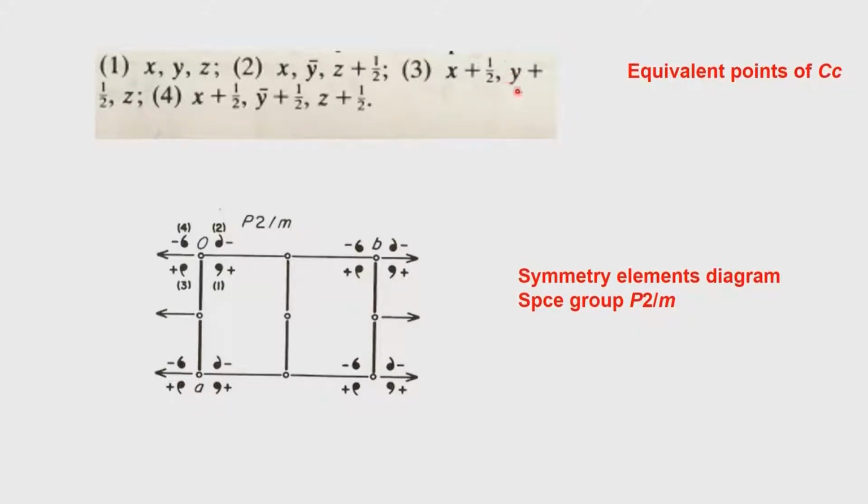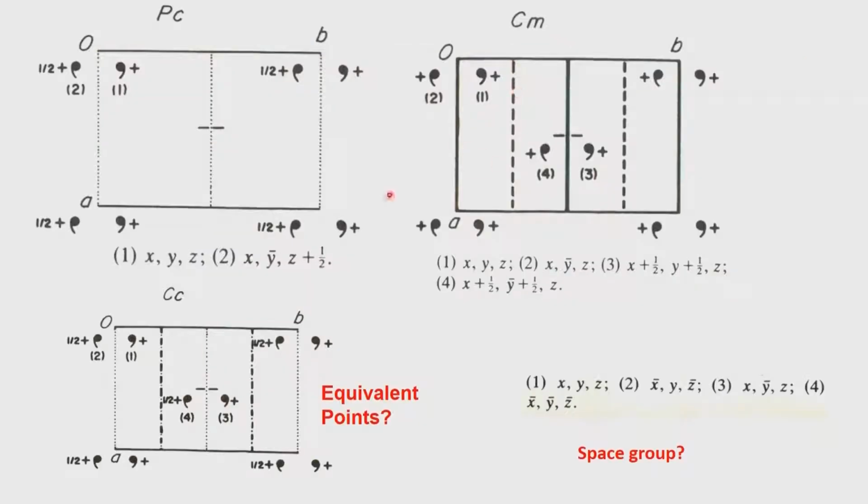So, this therefore now brings us to the understanding of 2 of the symmetry elements. In fact, today we have seen the CC, the presence of the mirror point group symmetry. We have also seen the presence of 2 as well as a perpendicular mirror. So, this space group analysis now tells us about the fact that we are now looking into the center of inversion related space group. All the earlier space groups PC, CM, CC belong to the non-centrosymmetric space group.